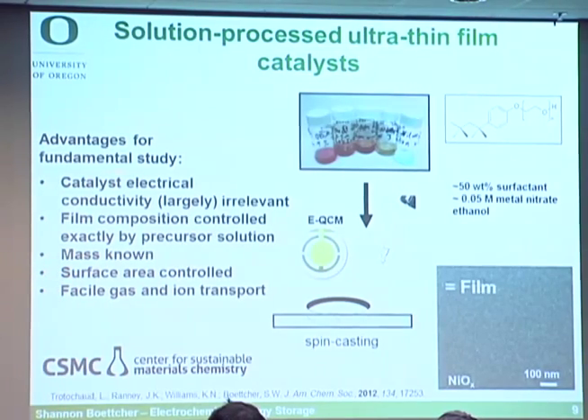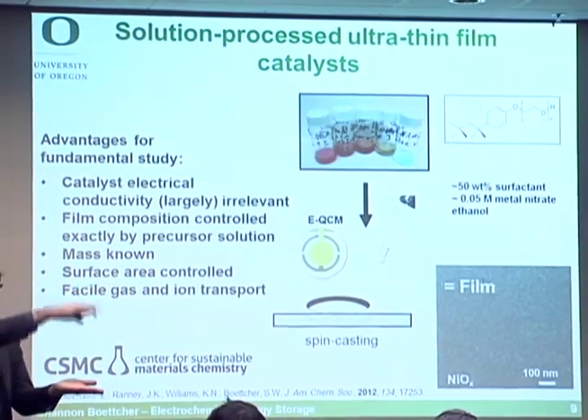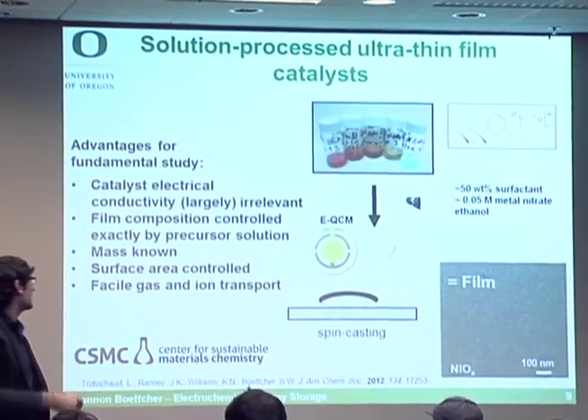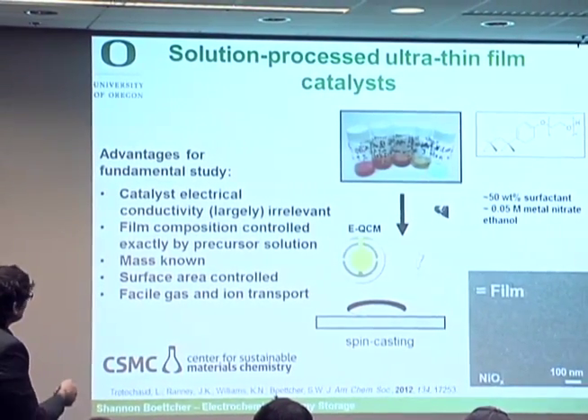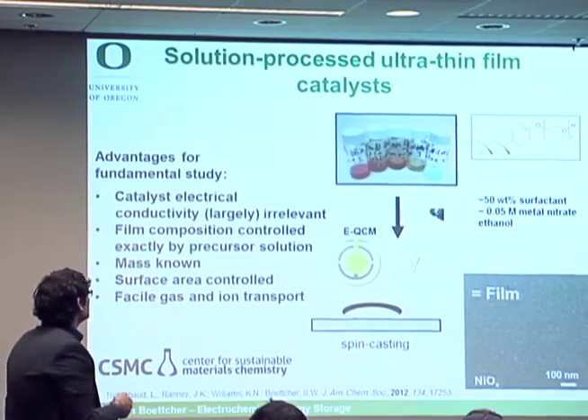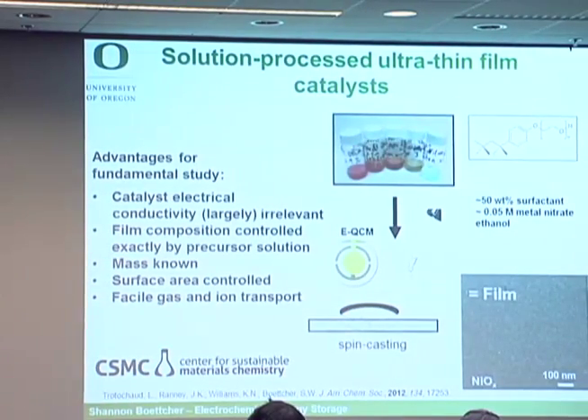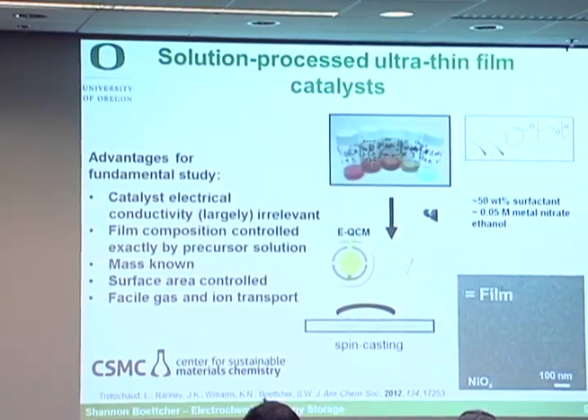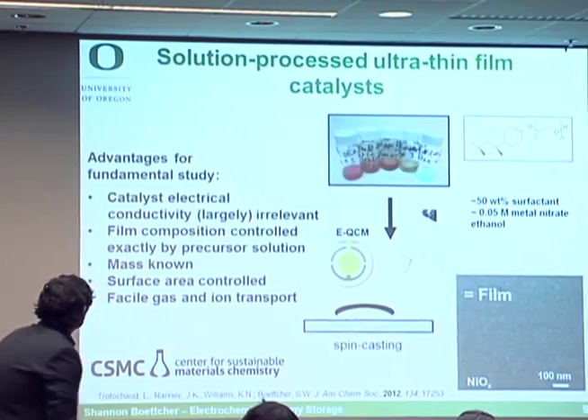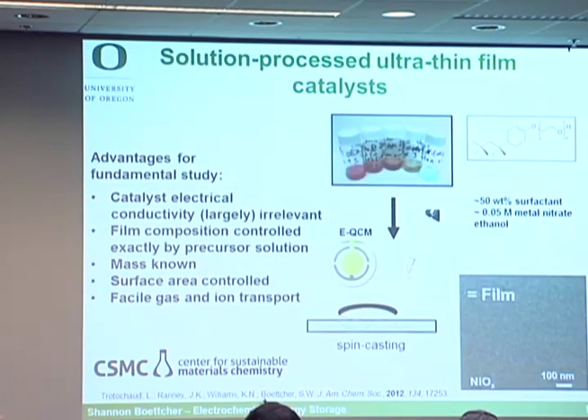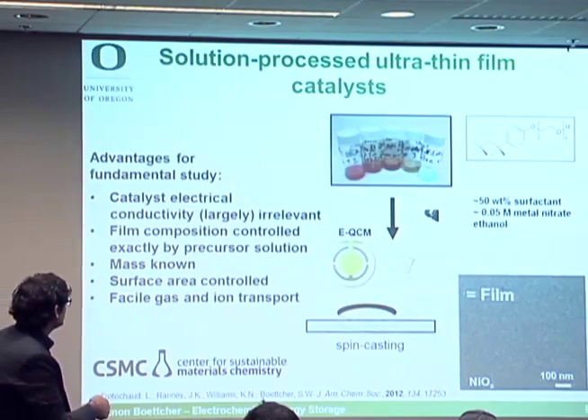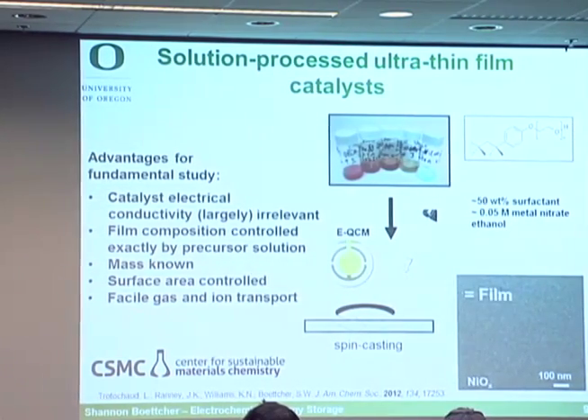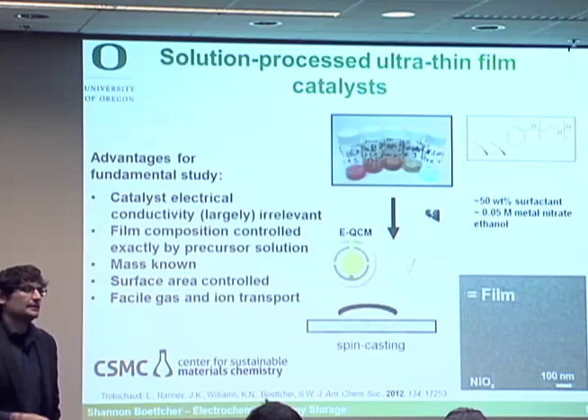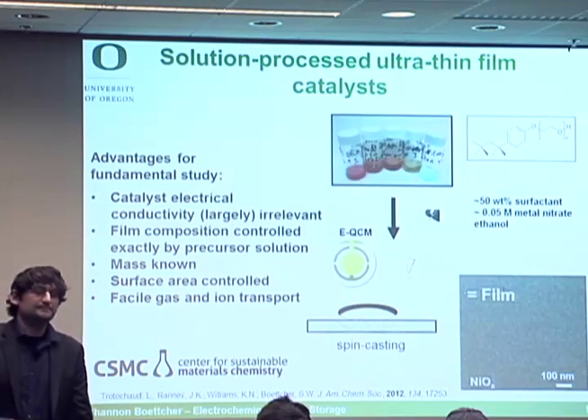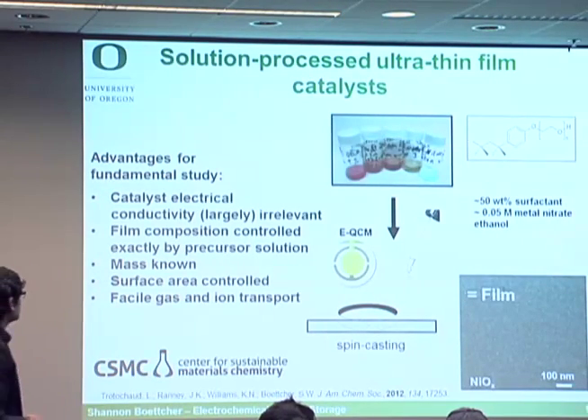If it's a very thin film, the lateral conductivity is not that important because it's thin. The electrons don't move very far. We're going to use solution processing, just simple salts and surfactant to break the surface tension, to make relatively smooth, thin films. The surface area we know because it's basically the real surface area. And gas and ion transport is fast because you don't have a lot of porosity. Okay, so that is our approach.